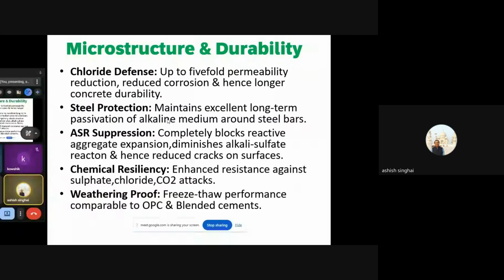Then a very important function that we always ignore in most big infrastructure projects is ASR. We always test the cement, admixtures, even steel is tested phenomenally, but the one thing which remains ignored is ASR, that is the aggregates, our coarse aggregate and fine aggregates. They are not tested chemically to that extent, but these coarse and fine aggregates also have some kind of chemical constituents, and when they are integrated into the concrete, obviously their impact will come into play, and we observe alkali silica reaction in the form of prevalent cracks that appear on the surface. Sometimes they go deeper into the concrete, and possibly they can damage the reinforcement embedded inside. So ASR is a very, very important function which we need to pay attention to more often than not. It is generally what I've observed along my career, that it is not being given that much importance, but it has to be given.